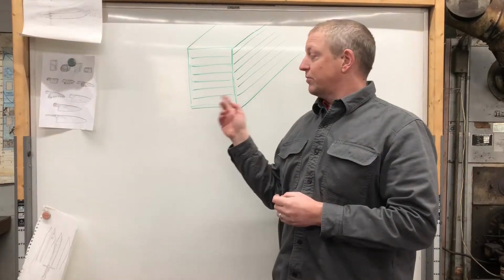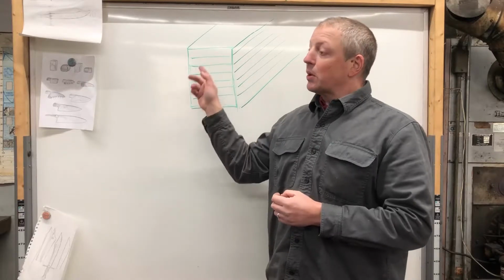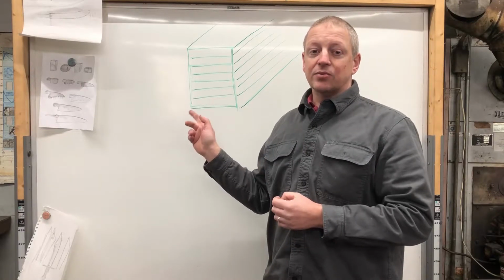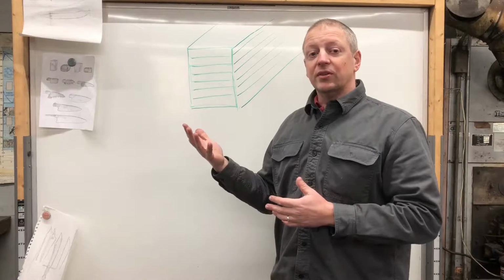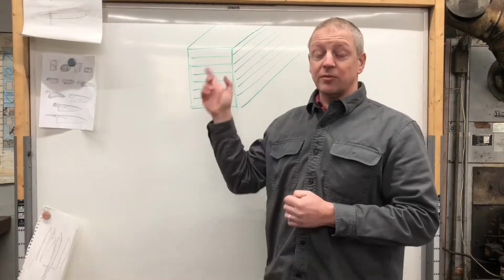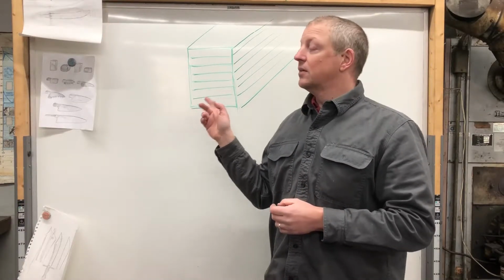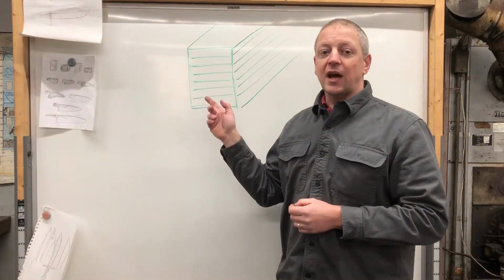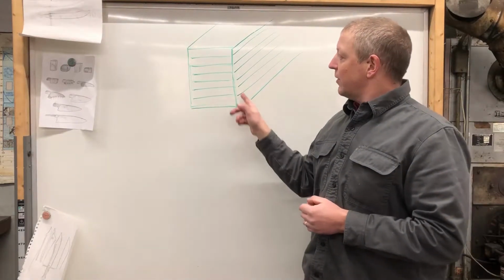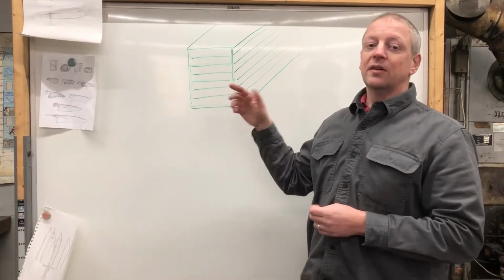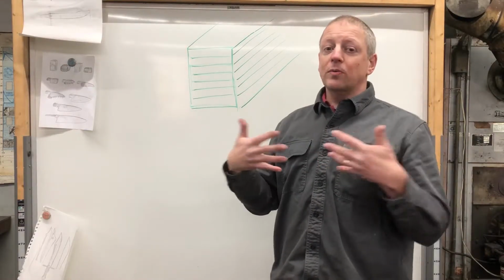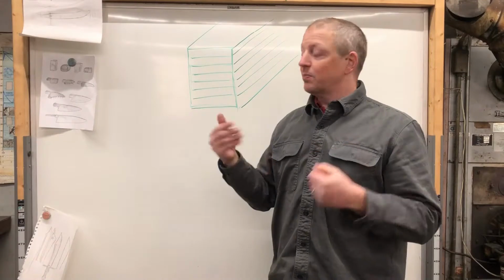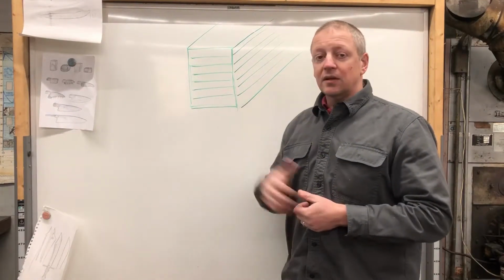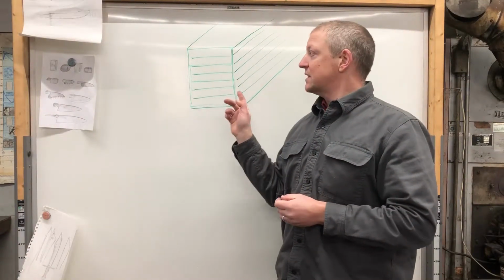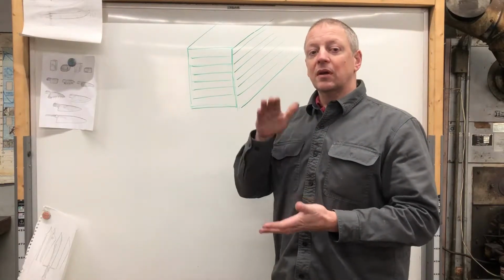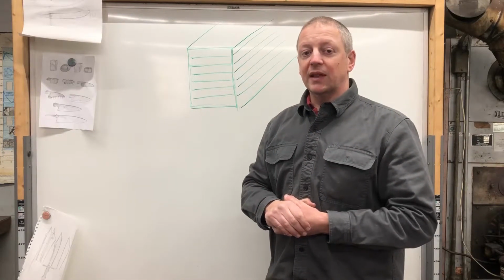If you find that you're getting deeper seams at the outside and it's really becoming an issue, one thing you can do is, after you've set your weld, flux the outside. That will give you that protective coating. This flux won't penetrate between the layers, but it will help seal up these little seams, and you'll probably be able to get that last little bit of weld.